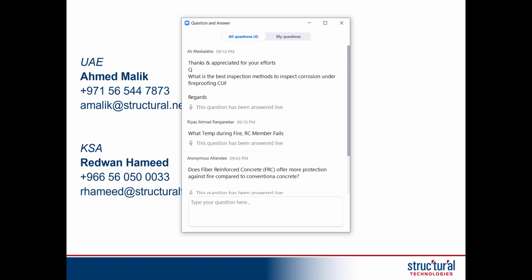And not only because of the weight associated with it, but they have done through testing and have found that the placement of these plastic fibers, when it's subjected to heat, the fibers themselves melt within the concrete and then form these previous channels, meaning the relic indicators of where it once was, because the plastic melts away. So there's additional essentially cavities within the concrete, very fine because these fibers are very fine, but they're well distributed throughout the concrete mixture, and it provides additional insulating value. So that's a great question, and it's something that has been proven through research, and primarily as it's being funded by the petroleum producers and downstream manufacturers and refiners.